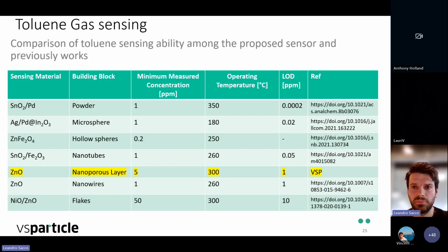And we are very proud of these results, because if we compare with the existing literature, we observe that this limit of detection is very good, around 1 ppm. But what I really want to point out here is that there is still a lot of room for optimization. Here we just print some lines and use it as a gas sensor, and already we are among the 10% best sensors reported in the literature. So this is a very promising result.